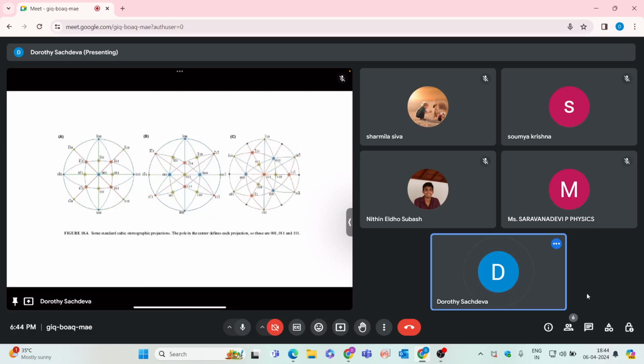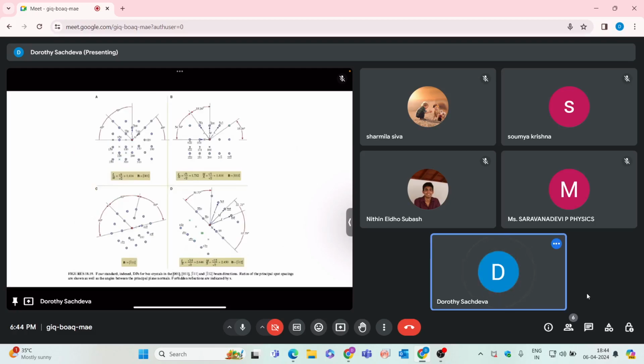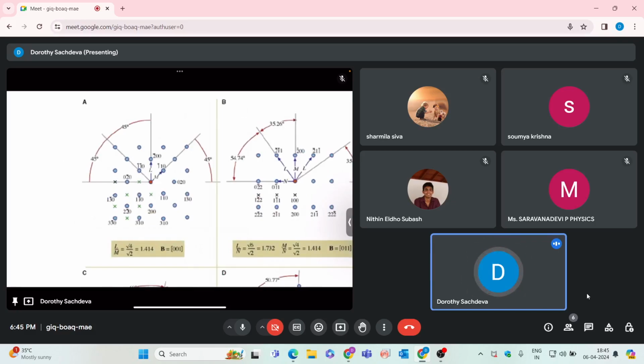So for the indexing of your diffraction pattern, let me zoom into one of the diffraction patterns. Suppose this red one is your central spot, then you have to determine at least three. If you have determined two non-collinear directions, then you can tell all the other spots in your diffraction pattern. Okay, suppose this is your M and this is your L. So you have calculated this distance M and this distance L. So the ratio of these two distances is 1.414. Then for the cubic system, this zone axis will definitely be 0, 0, 1.